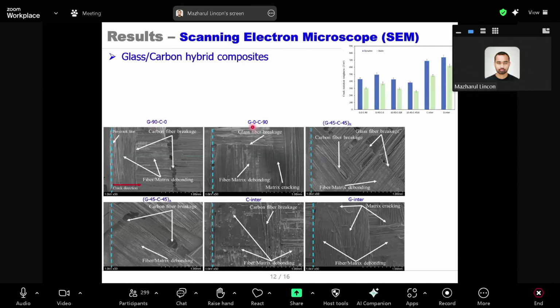On the other hand, in the G0C90 case, glass fiber breakage happens as well as fiber matrix debonding and matrix cracking. However, no carbon fiber breakage is observed in this composite type. As we know, carbon fiber needs much higher load to break than glass fiber, that's why this G0C90 composite shows less fracture toughness value compared to G90C0.